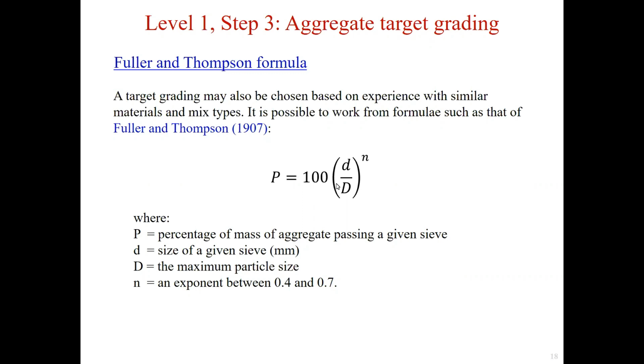So P equals 100 times D divided by capital D to the power of N. In this formula, capital P is the total percentage passing a given size. If we know the size of the sieve D, the maximum particle size capital D, the exponent could be taken as a value between 0.4 and 0.7 to represent boundary values.